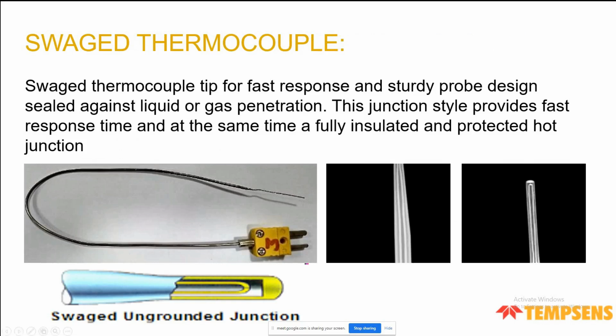Then we also do swaged thermocouples. These are reduced tip thermocouples. The thermocouple measures its own temperature, so as the mass is smaller at the tip, it will give you a faster response. For example, a 0.25 millimeter thermocouple can have a response of 30 milliseconds. So with the reduction of the tip, we get a fast response, and with the higher diameter of the extended portion, we get more strength. This is being used in a lot of industries to get faster response and good mechanical strength. We supplied also to GTRE and a lot of customers like this, IGCAR and VSSC, some of these sensors. We have in-house radiography and other measurement facilities, so they all can be checked and measured in the company.